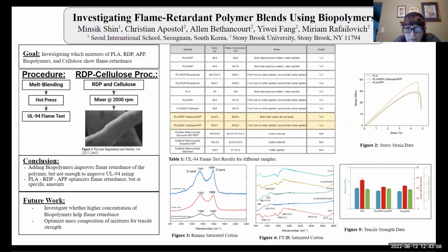We've also done Raman spectroscopy on the char of the solution columns. The presence of the D band and the G band from the Raman shows the formation of disordered carbon structures. We also note in the FTIR data that for the APP and RDP solution, or just the APP solution, there is the presence of the phosphorus oxide peak in the FTIR, which shows char, which is what we want for a flame retardant solution.